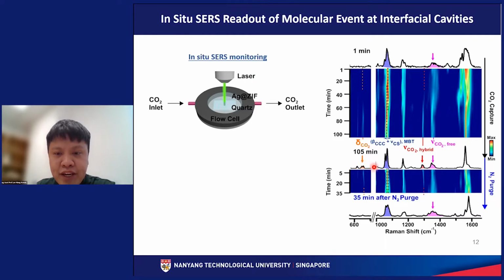wave number. Okay. Again, after which we try to flow our gas flow cell using nitrogen. The purpose is for us to determine whether all this spectral evolution is due to physical or chemical interactions. Okay. So when we flow the gas flow cell with nitrogen, we see that there is a reversal in our spectral evolution. So simply to say, what we are observing over here will revert back to our initial state. So after purging, the SERS spectrum looks very similar to what we have at t equal to 1 minute. So this tells us that the change to the SERS spectrum is due to physical interactions rather than chemical interactions.